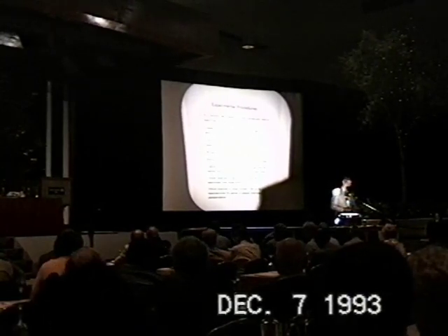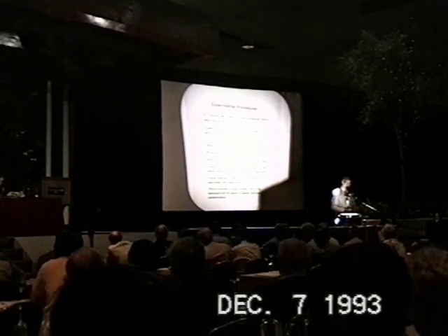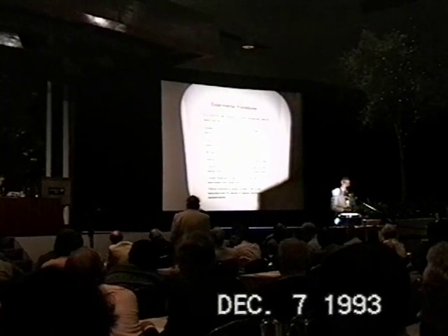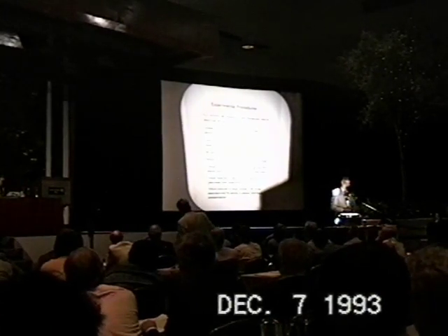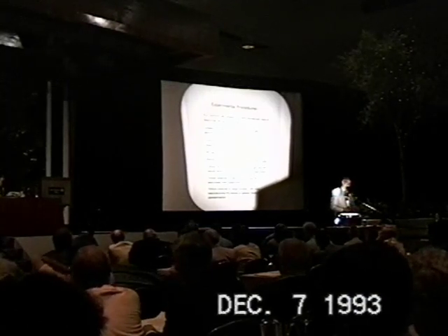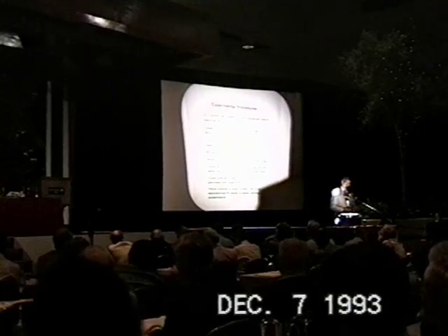We used those cells systematically, always with internal H2/O2 gas recombination such that the recombined water was easily driven back into the cell electrolyte. Hence, and this is a very important point, we are not concerned at all with separation effects between hydrogen and deuterium. We also determined continuously during the experiments the H/Pd or D/Pd loading ratio, and I will say a few words about this in a moment.